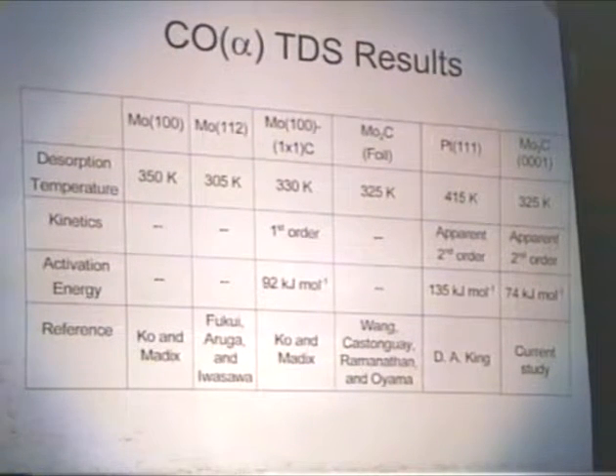Finally, the last one that I've included is the platinum 111, which, as I mentioned before, has the identification of this apparent second order kinetics for CO desorption. While the temperatures don't necessarily match, what we are interested in is this behavior and the possibility that we have desorption through a precursor state.